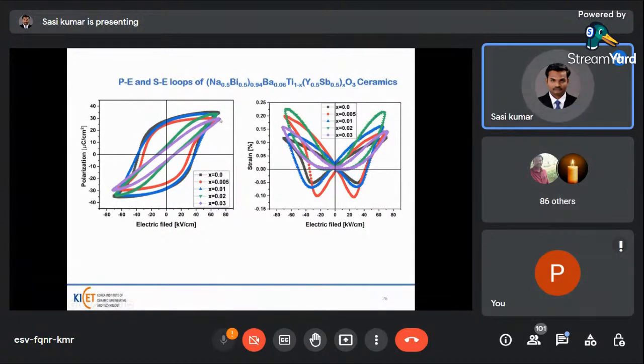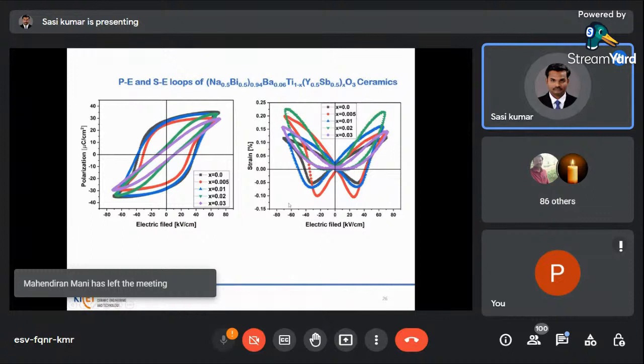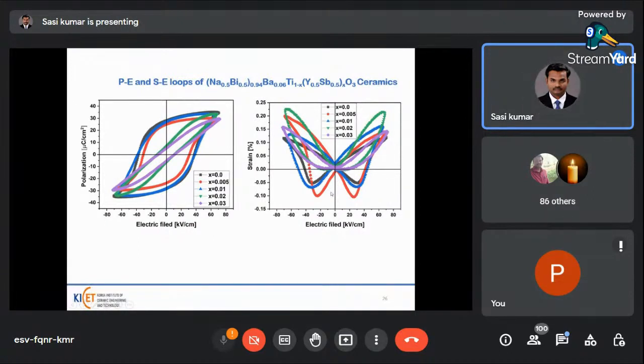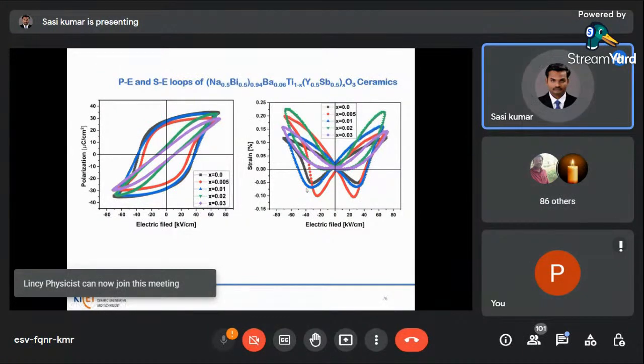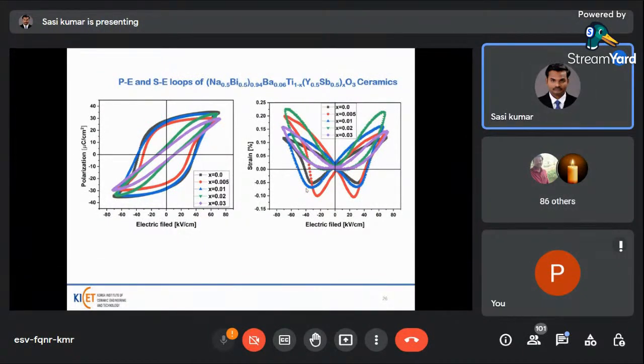Here a higher electric field is applied to that material, and the polarization is around 35 microcoulomb per centimeter squared. Here the SE loop shows butterfly type loops for all the compositions, and the x equal to 0.02 composition possesses the higher strain value, around 0.22% strain is observed in that composition. This is mainly due to both different structures coexisting in these particular compositions.